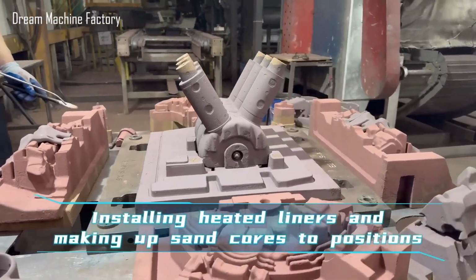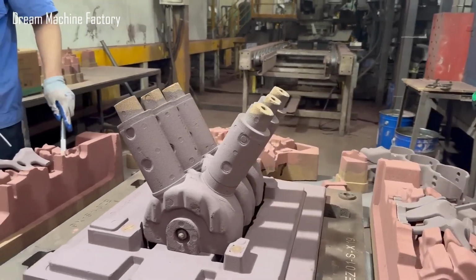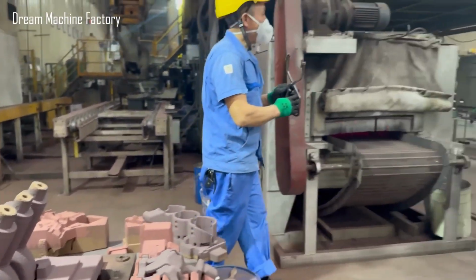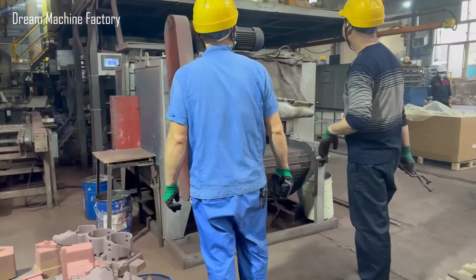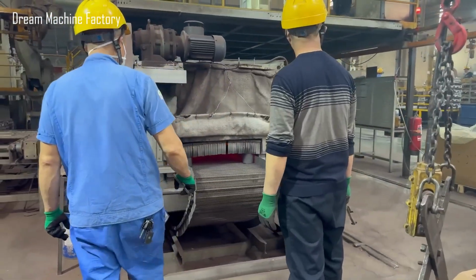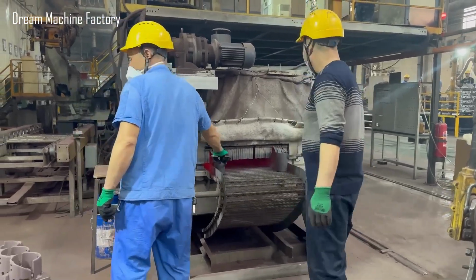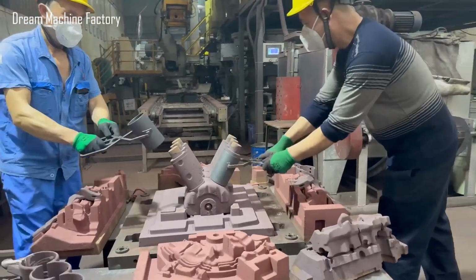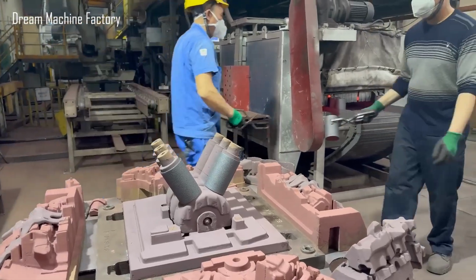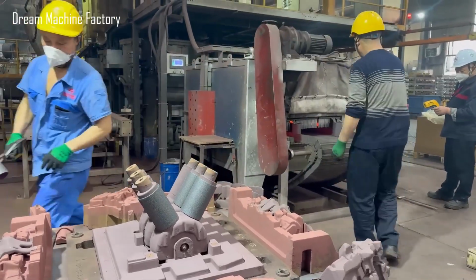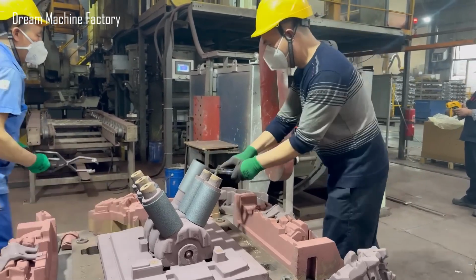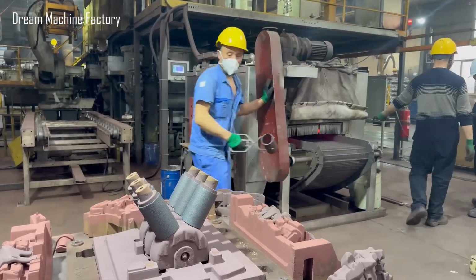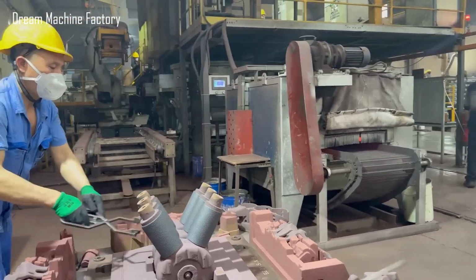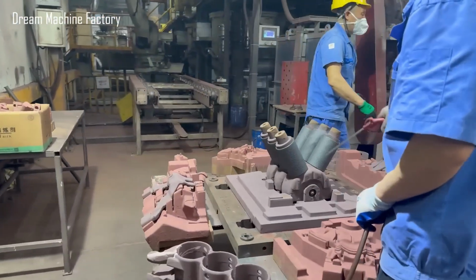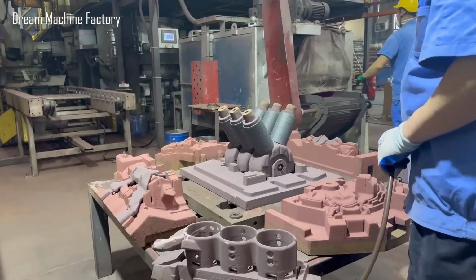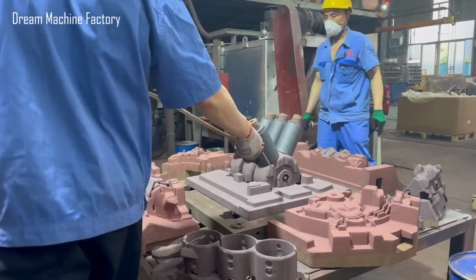In the V6 engine block casting process, installing heated liners and accurately assembling sand cores are crucial for ensuring dimensional precision and metallurgical quality. Cylinder liners, typically made of cast iron or steel, are preheated to a specific temperature, usually between 150 degrees Celsius and 300 degrees Celsius before installation. Preheating the liners serves several purposes. It reduces the temperature differential during casting, minimizing thermal shock, and it promotes better metallurgical bonding with the surrounding molten metal, improving the structural integrity of the engine block.